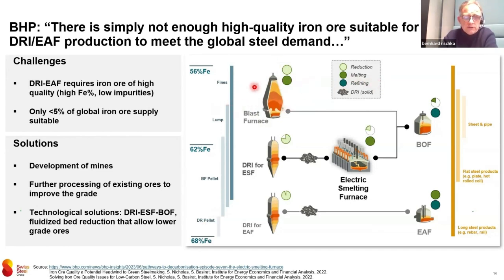However, if we want to close down this route, and this is what's happening in Europe, especially in Germany, we started with Salzgitter, we have Saarstahl, we have ThyssenKrupp. ThyssenKrupp is a little bit different, but then we have to move to this process, the one I described before in the Middle East, where you have a DRI plant reducing the iron ore with natural gas. And most of the time, since both the DRI plant and the melt shop are adjacent, you have a hot charging, a direct link to the electric arc furnace. So you have bunkers on top of the electric arc furnace and can feed the DRI with 500, 600 degrees, which makes the furnace much faster.